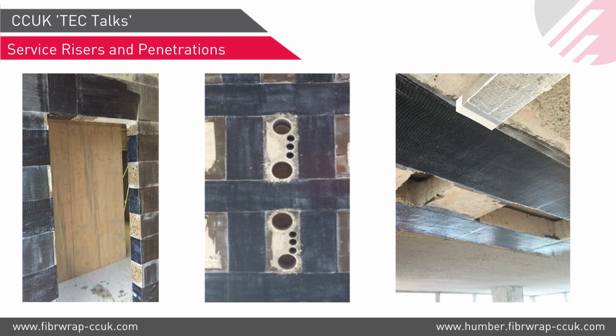So it's the same sort of trimming, but that is done using FRP. Yes, so it's basically you work on the same principles of trimming here, but again, because when you cut these kinds of cores, you will cut some rebars in the slab. Those rebars will generate additional forces in the surrounding area, and you design FRP for those additional tensile forces. So that's a very straightforward design principle on that.